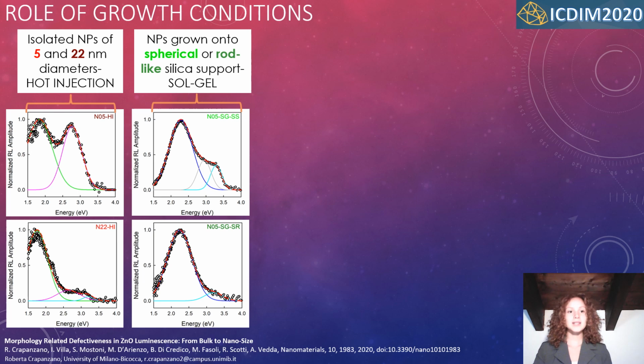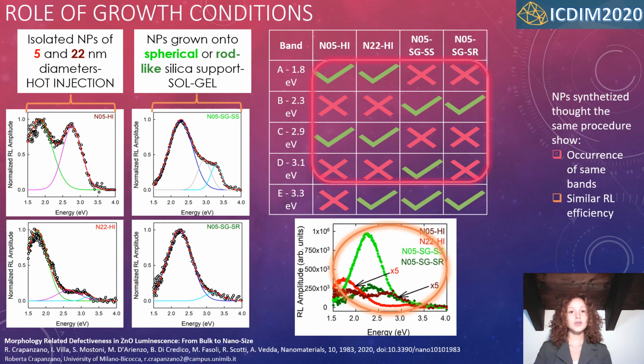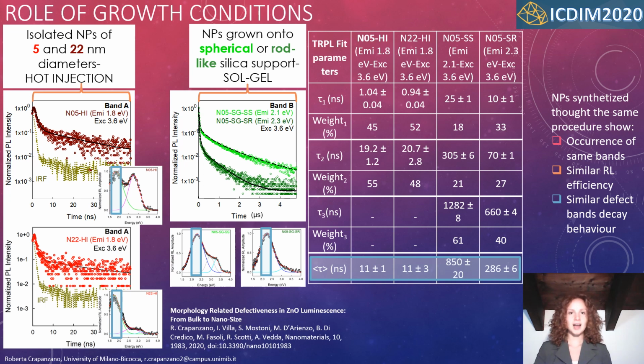To examine the role of growth condition, we will focus only on the 4 nanoparticles. In particular, I recall that the 2 bare nanoparticles are grown by the hot injection method, while the 2 silica-supported nanoparticles are grown by the sol-gel procedure. First of all, nanoparticles synthesized by the same procedure display the same emission bands that also have a similar radioluminescent efficiency. Moreover, the decay times of the same bands of nanoparticles grown by the same synthesis are of the same order of magnitude. In particular, for the bare nanoparticles, the decay times are the same, while for the silica-supported nanoparticles, a slight difference is observed.